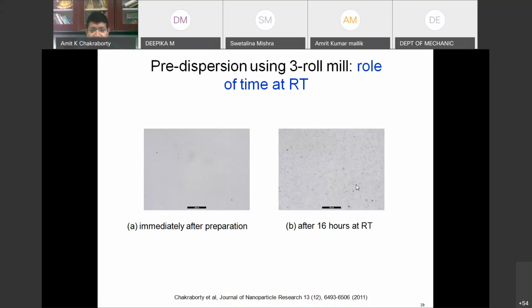We also studied the influence over time: immediately after preparation of the dispersion, and after you leave it for 16 hours. What we observed is that after 16 hours, some dark particles appear. This means mixing them is not enough. You also have to maintain the dispersion. Mixing and maintaining are two separate things. You make a very good dispersion, but you have to withstand it for a long time. That is not happening, because after 16 hours we see some particles being formed.